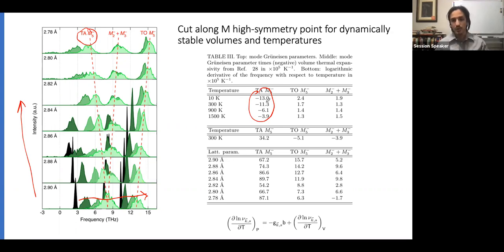The Grüneisen parameter is negative and it's large, about an order of magnitude higher than what you expect. In most materials, it is about two. This is the anharmonic part, the anharmonic shift. You can see that it is in the opposite direction as the quasi-harmonic shift, and it's also an order of magnitude, sometimes higher than for the other two modes. In this case, all of them increase their energy or frequency with temperature, but the TA M5 increases more. And of course, the quasi-harmonic is against it.